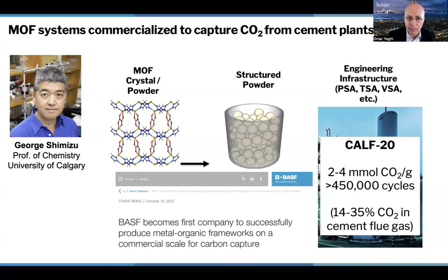So this is a big blockbuster, I would say, application for MOF, and it is already deployed to prevent CO2 from reaching the atmosphere. And this is especially true for these cement plants where the CO2 concentration in the flue is much higher than it is in the air. And so this material is really applicable to this application. So this is a very exciting result.